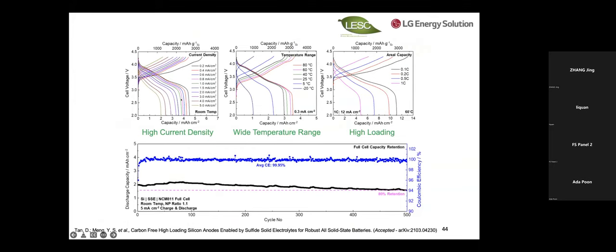And this is the reason we were able to go for very high current density, have a wide temperature range, and also really, really good area capacity. This kind of area capacity can only be achieved by dry electrode process. So we were very fortunate to showcase the complete dry process of the cathode in this solid state battery work.